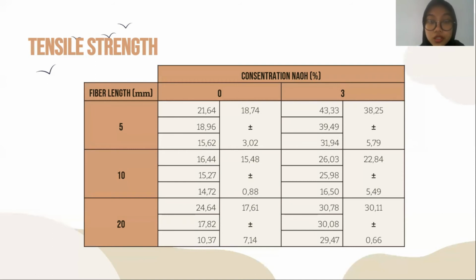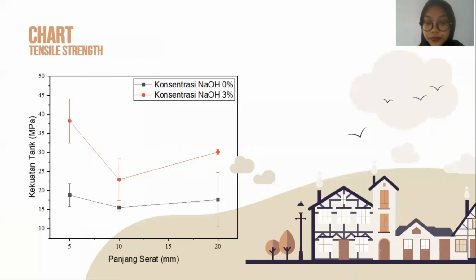Meanwhile, at the 3% natrium hydroxide concentration, the highest tensile strength was also at a 5 millimeter fiber length. Fiber lengths of 5 millimeters, 10 millimeters, and 20 millimeters had the highest tensile strength in fiber with 3% natrium hydroxide immersion. This happened because bagasse fiber, which underwent a delignification process with the addition of natrium hydroxide, experienced a reduction in lignin, which increased the ability of the fiber surface to bond with the matrix. So bagasse fiber that undergoes the delignification process with 3% natrium hydroxide has greater tensile strength. This is the chart of tensile strength for all variations in this research.